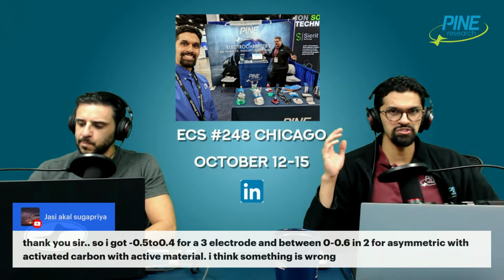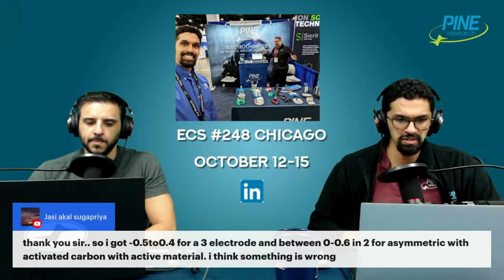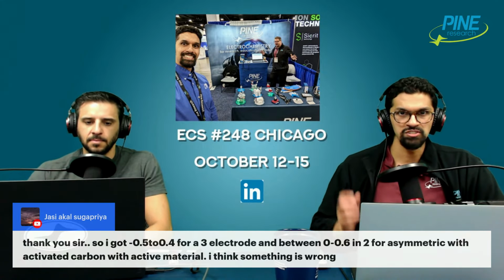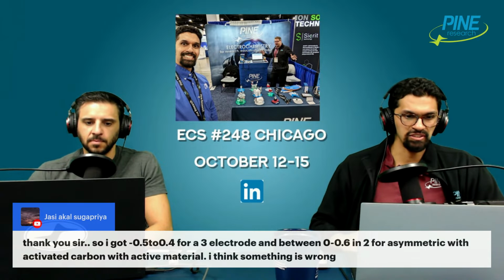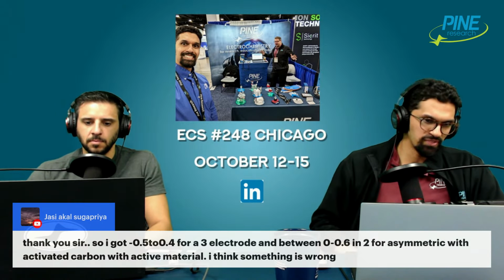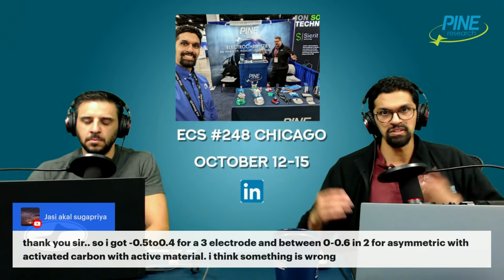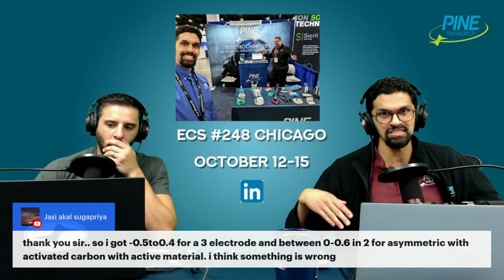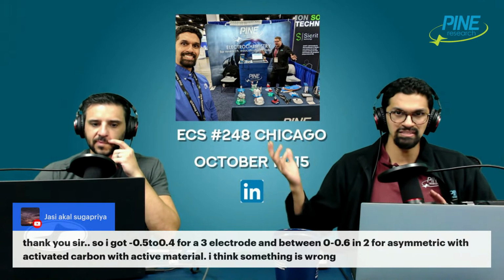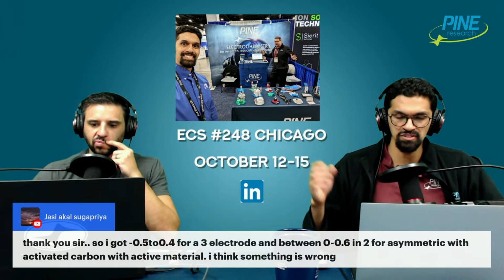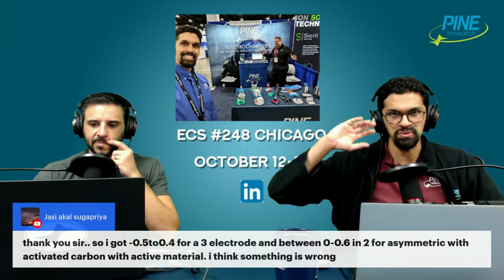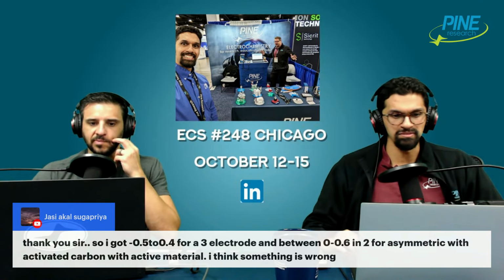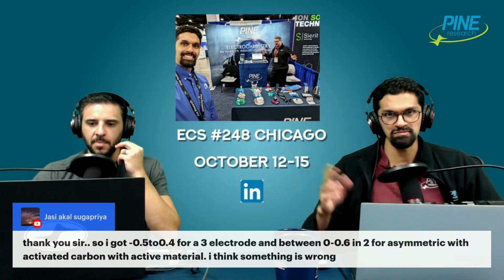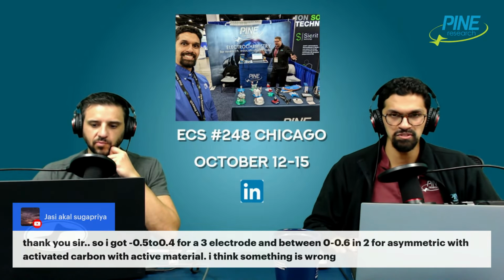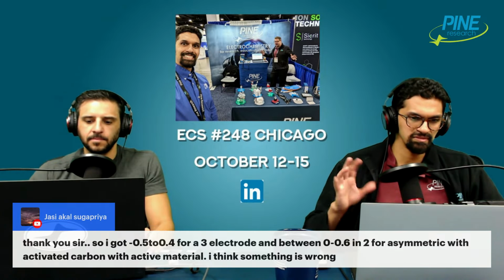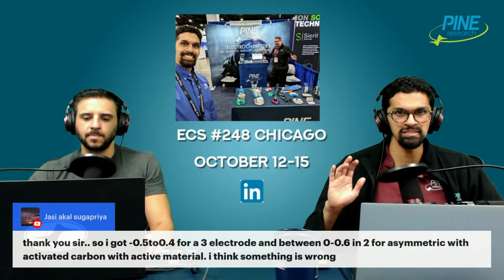I'm not surprised that you have a slightly smaller voltage range or potential window for the 2 electrode versus the 3 electrode, just by nature of how the experiments work. The fact that they're also very different: one is minus 0.5 to 0.4, and then one is 0 to 0.6. Well, there's a reference electrode in one case, and there's not a reference electrode in the other case. So it's hard to say where those relative things are. The 2 electrode asymmetric one also isn't like plus 2.0 to 2.6. It's like, okay, it is still kind of in the same realm, if you will. So that's my thinking about the numbers that you got. It doesn't hit me as like they're wrong.